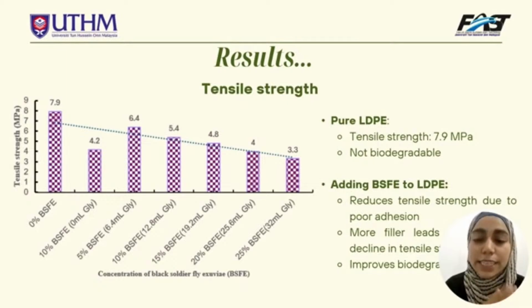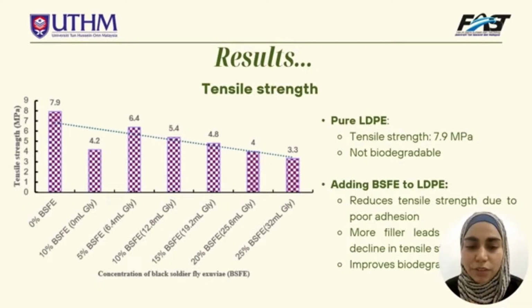If you see the graph, this graph shows that as the black soldier fly exuviae content is increasing, there is a decline in tensile strength. This effect intensified as the filler content is increasing. So in other words, we can say that lack of strong adhesion between the components is the reason behind the decline in tensile strength. The first one is LDPE, which has a high tensile strength of 7.9 megapascal.